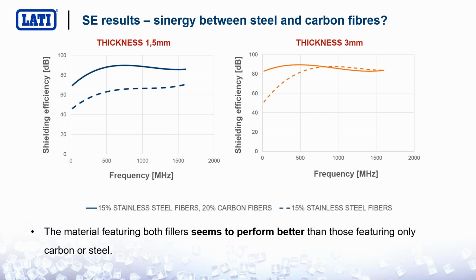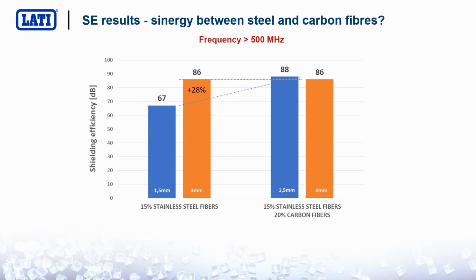What is the reason for this? We thought that the main reason is due to the orientation of the carbon fiber, especially in the low thickness. In this graph here, you can actually see how the 1.5 millimeter thick mixture of steel and carbon performed better than 3 millimeter of only steel.